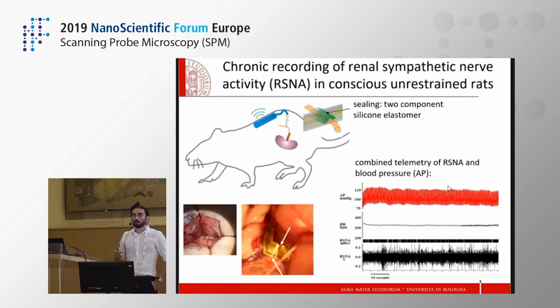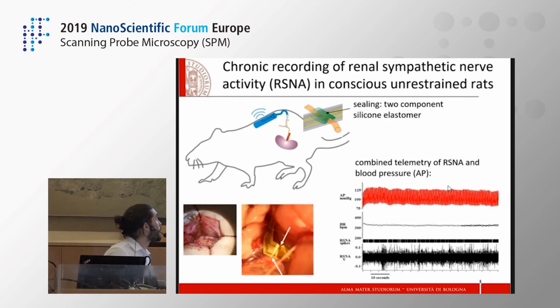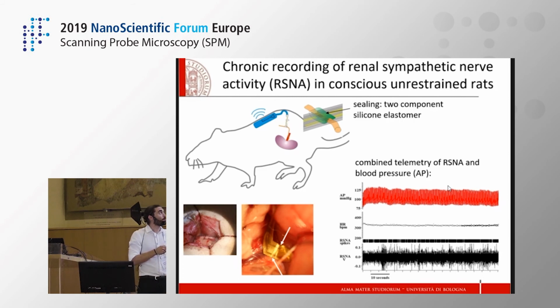In order to test our devices, we did a chronic recording. We implanted on the renal nerve of rat, and we did a chronic recording using a telemetry system that was placed subcutaneously to the rat, together with blood pressure monitoring, always with the telemetry system. In this case, this is the implant, and we placed the trench below the nerve strand, and then we sealed it with silicone in order to keep the electrode stable.